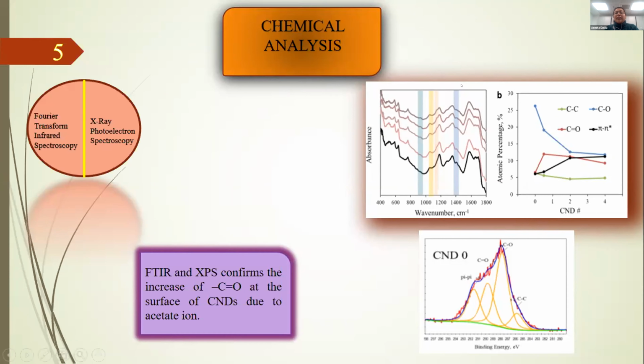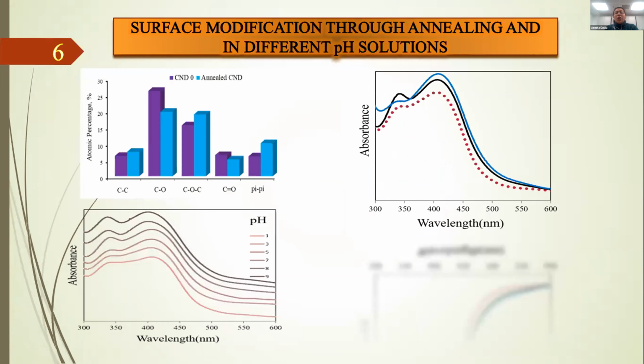From both FTIR and XPS, it is confirmed that there is an increase of oxygen at the surface of CND due to acetate ions. We also tried 2 different kinds of approaches for surface modification: one is annealing, another one is trying different pH solutions. As you can see, in different pH solutions from acidic to basic, there is a huge impact on the shape of the 340 nanometer peak.